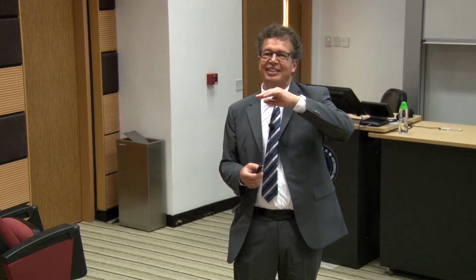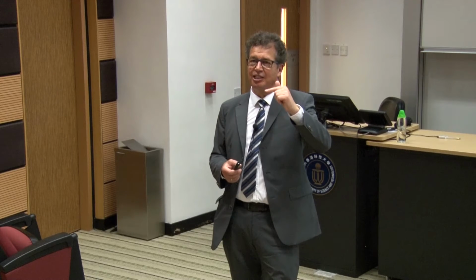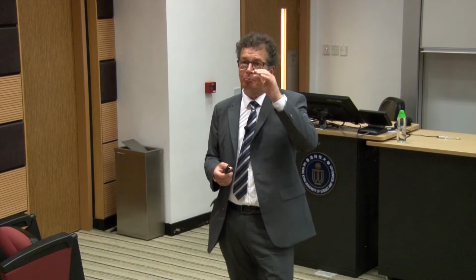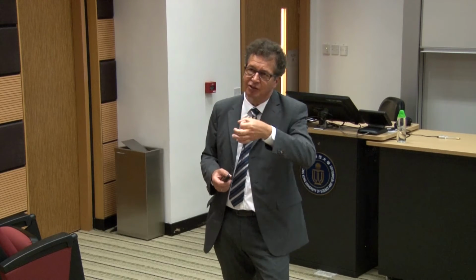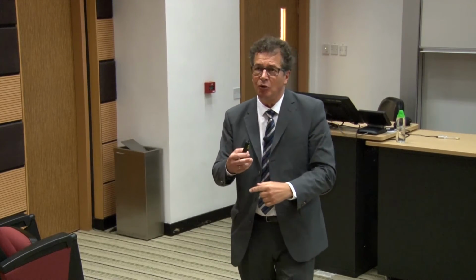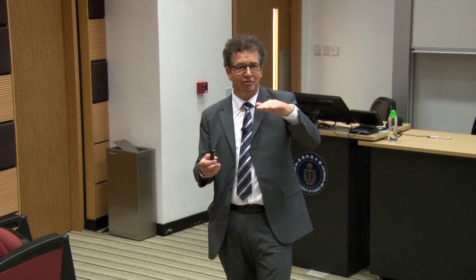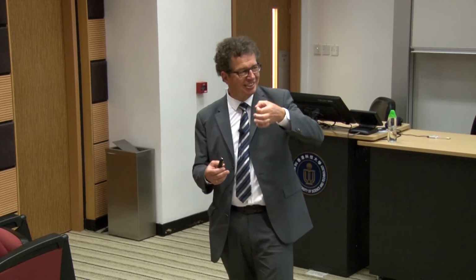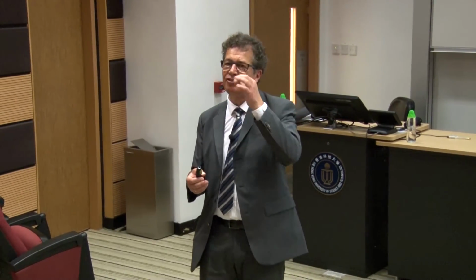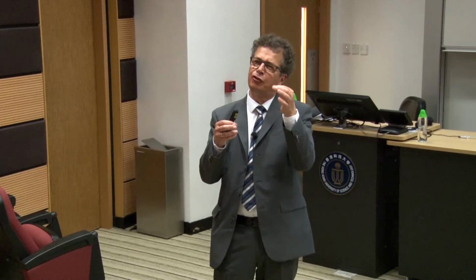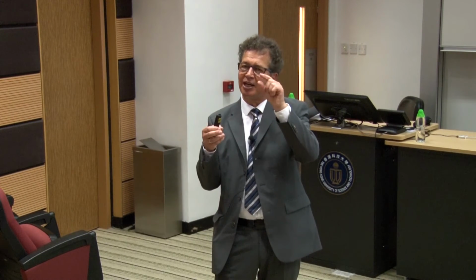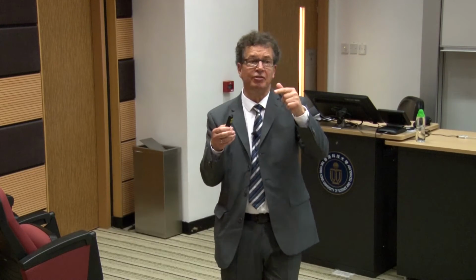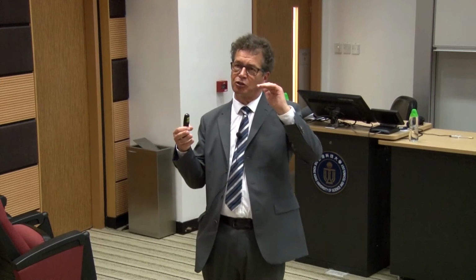energy level. So your redox potential will be controlled by the redox potential of the silver cluster, the gold cluster, and so on. And now, this is the Fermi level. The Fermi level is dictated by this cluster you have there. So you will have different Fermi levels. I showed you that only a few TiO2 or zinc oxide particles have this direct contact. They have a different Fermi level in the dark than the rest. 90% still have the Fermi level of the TiO2 and are not controlled by the silver.